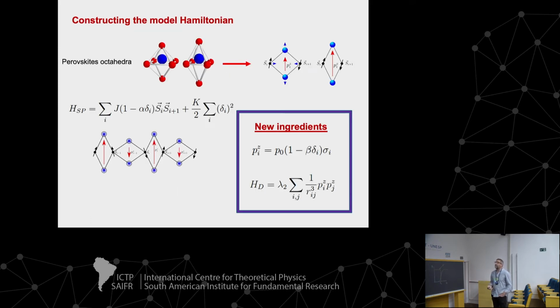OK, so let me go to the model we proposed. Essentially, the idea was to simplify this structure into this. So what are these arrows and dots here? Essentially, we have a magnetic system, which are the black dots. We started with a spin-one-half system, but it could be higher spins. And due to the electric environment, some different electric charges or whatever is around within these units, it could be, for example, the Jahn-Teller distortion that creates some electric polarization.